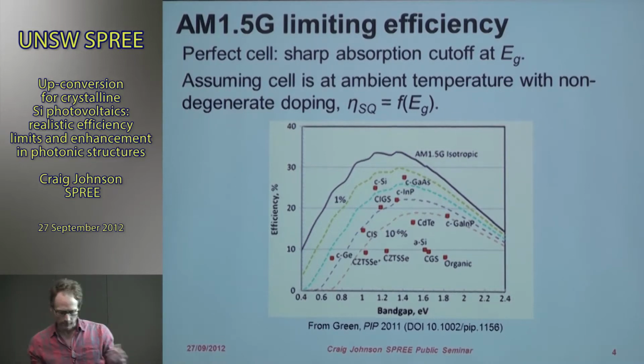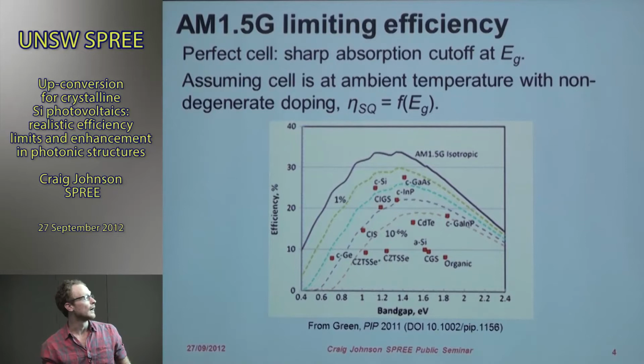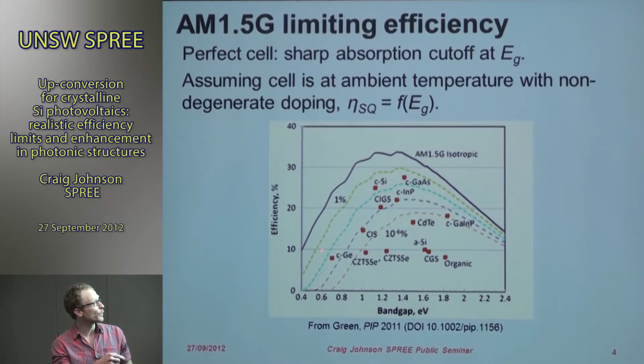So really, of course, the theoretical limit is going to come when the thing has a perfect quantum efficiency. Any recombination within the cell emits a photon rather than dissipating that energy by non-radiative mechanisms. But it's worth looking at what happens when you have 1% radiative efficiency and even lower. And those are the dashed curves there.